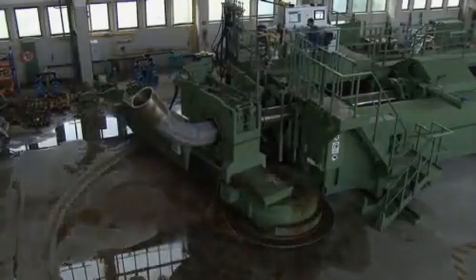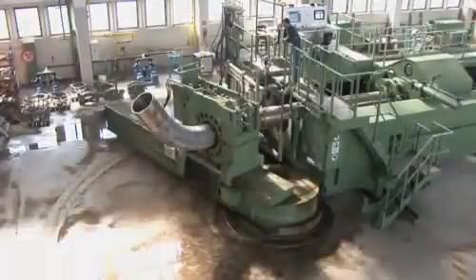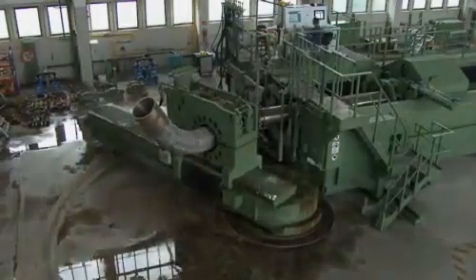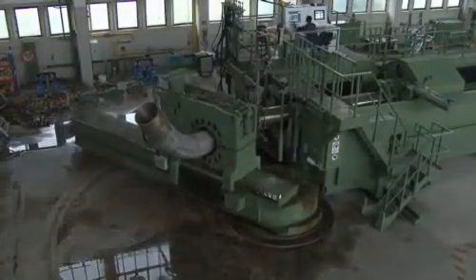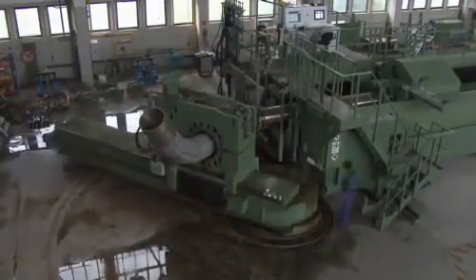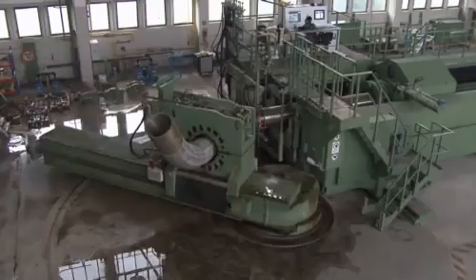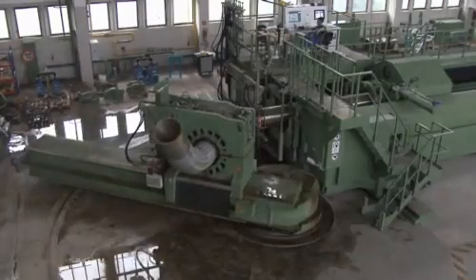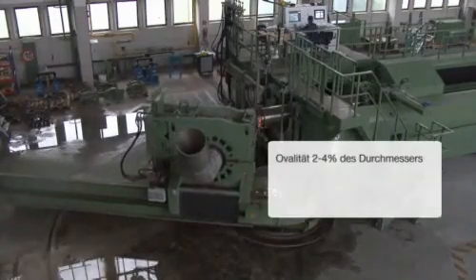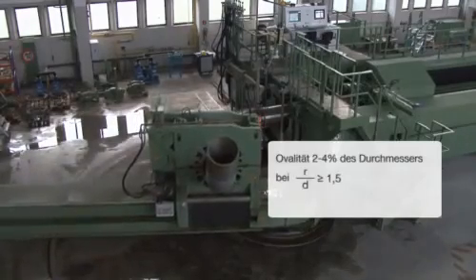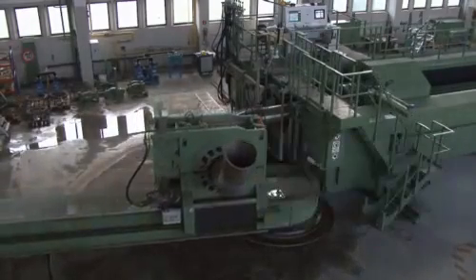The amount of feed is essential for the ovality of the bend. This is strictly specified, taking into account the long-term properties of the bend. The ovality shall be less than 2 to 4% of the pipe diameter. FINOW Rohrsysteme is able to achieve these values even with tiny ratio of R to D equal to 1.5.